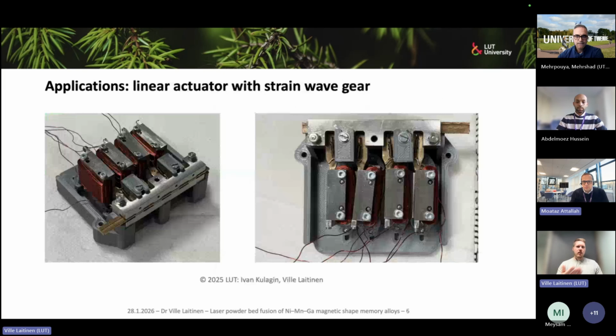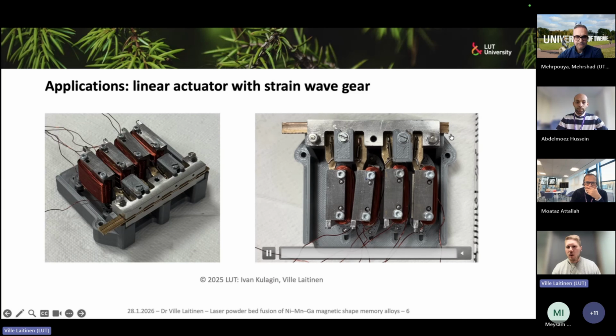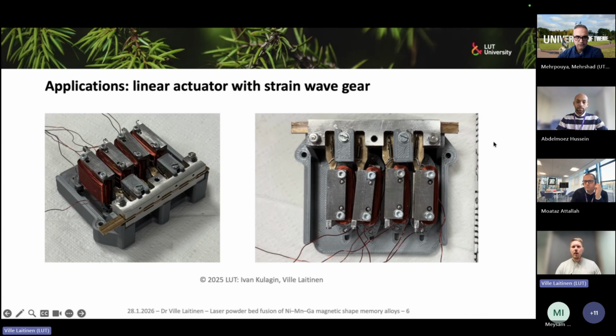Thank you, Ville. And then this is the linear actuator. In this linear actuator, you can see that there are teeth on this metal bar. The shape of those teeth is basically a triangle. We have a corresponding triangle shape at the end of these metallic bars that are connected to the MSM elements inside these electromagnets. It's difficult to see from this, but this corresponding triangle shape will engage the teeth, and because it's not symmetric, it will engage one edge and cause a pushing force which moves the bar in one direction. Then at one point this single stroke motion will lose contact with the edge.